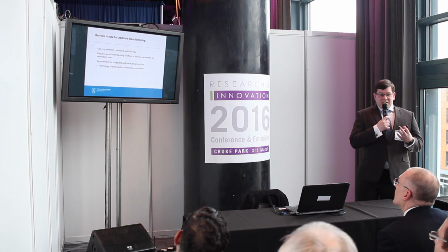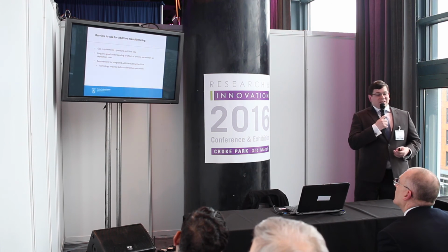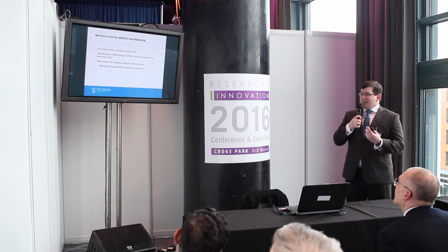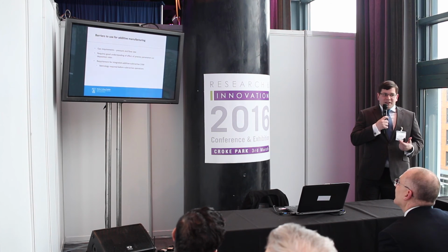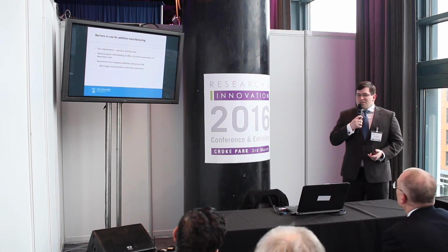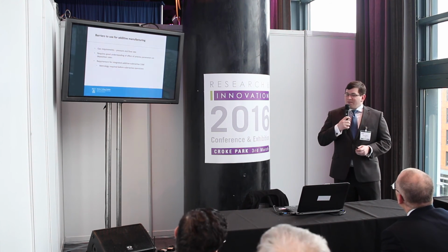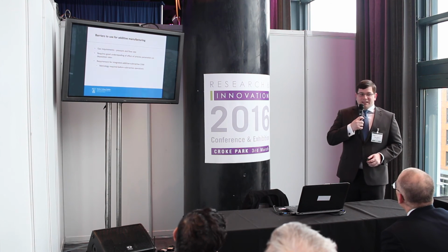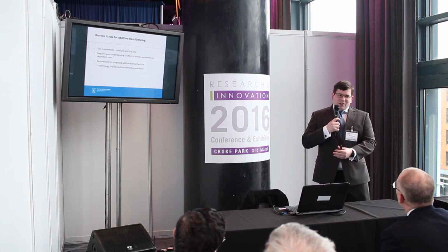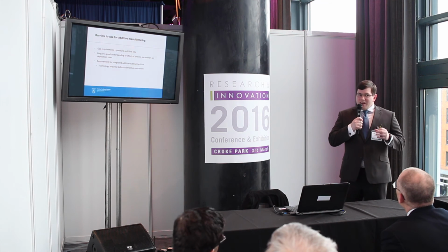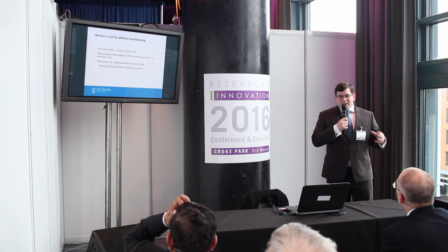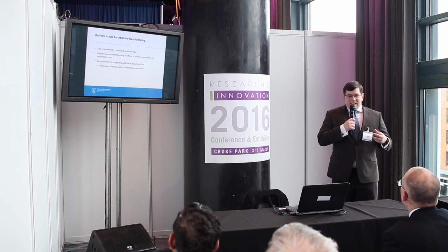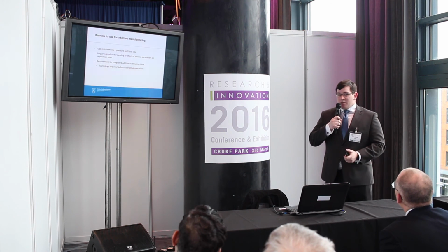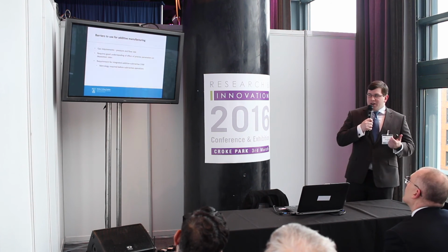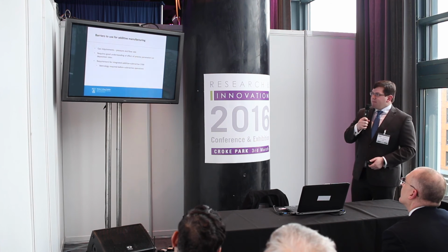So, the barriers facing additive manufacturing: if it was easy to use, everyone would be using it. What are the issues? First issue, and this is a cold spray issue, is the gas requirements. You usually need an awful lot of gas at fairly high pressures and fairly high flow rates. So you can't just put one of these around the corner in your office. You need a purpose-built facility, you need high-pressure lines in, you need a way of getting that gas in. And it can be quite expensive depending on what gas you're using and what kind of amounts you're using.